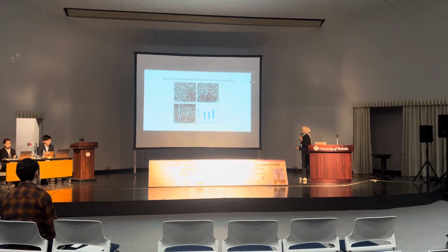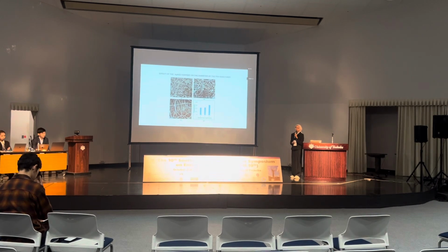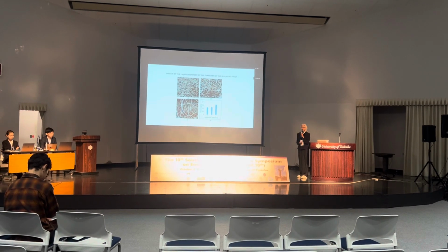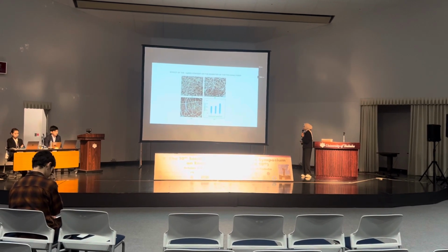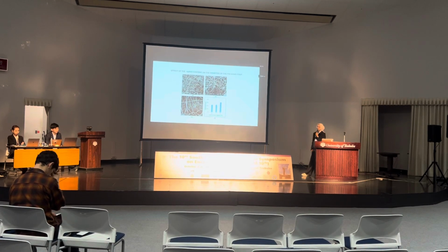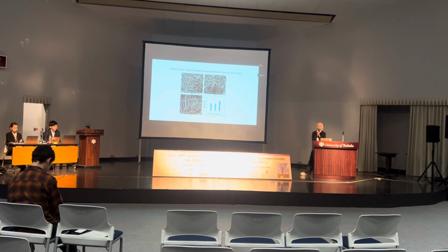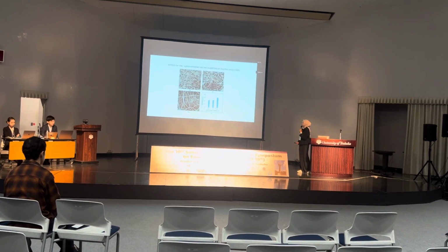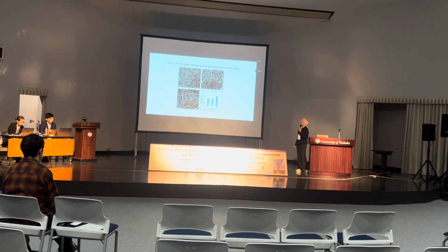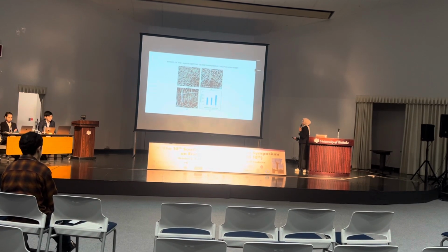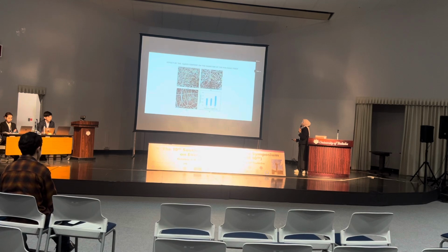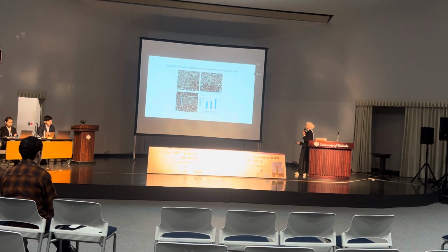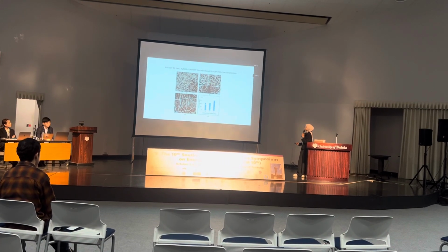I also investigated the effect of the silver nitrate content in the PVA nanofiber on the diameter. The results show that by increasing the silver nitrate from 0 to 1%, the diameter is slightly increased, while increasing further to 2%, the diameter is sharply increased.